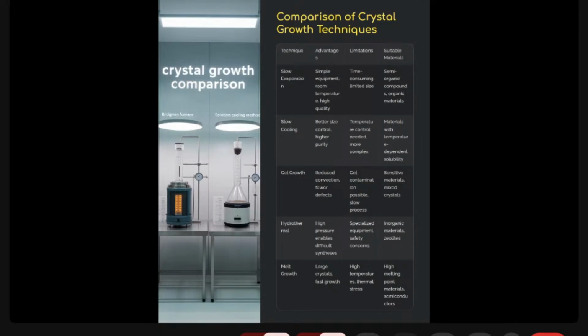There is a big advantage because it is low cost. Only a beaker and a simple magnetic stirrer are needed. It operates at room temperature, and the quality of crystal is also high, with good morphology and optical clarity. But one limitation is that it is very time consuming. I have done my research in the slow evaporation technique. All the crystals I have grown took 65 days, 70 days, 90 days to obtain the resultant crystals. So this is very time consuming.